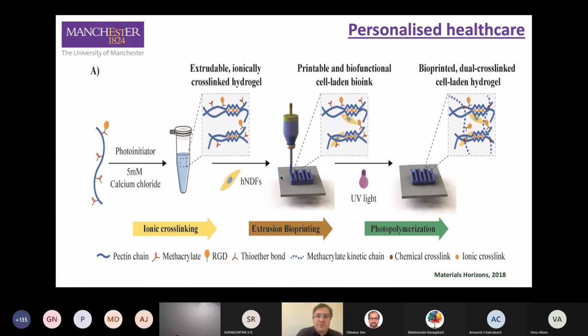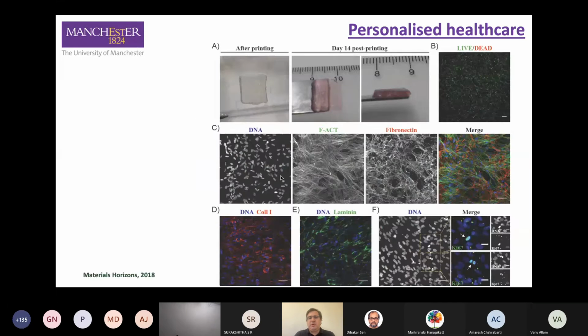We spent lots of time. We spent 3 years developing a proper bio-ink. We use pectin and we use a dual cross-linking approach. Basically, we pre-cross-link our pectin through ionic cross-linking to increase viscosity, facilitating the printing process. And after the printing, we irradiate to complete the polymerization. So we were also able to tune our bio-ink.